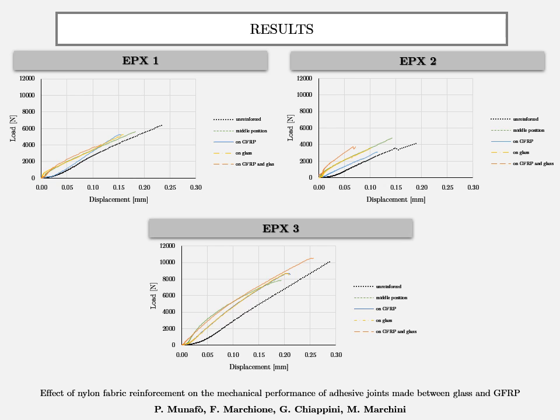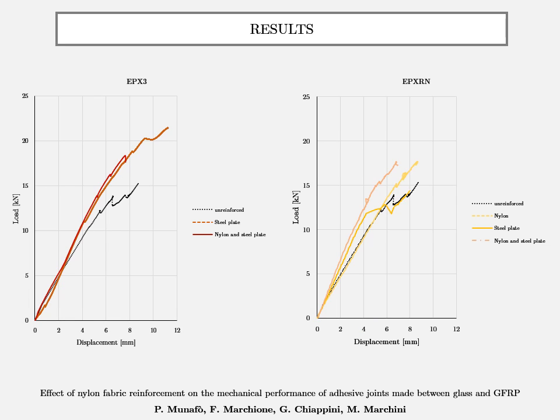In general, all reinforced configurations show an increase in stiffness. In particular, the joint configuration with reinforcement on the glass surface leads to a stiffness increase of plus 31%. For the first and second epoxy, a decrease in the ultimate strength values is observed, varying according to the combination tested. Plots give the average load displacement curves for the specimens tested in the 3-point bending tests.